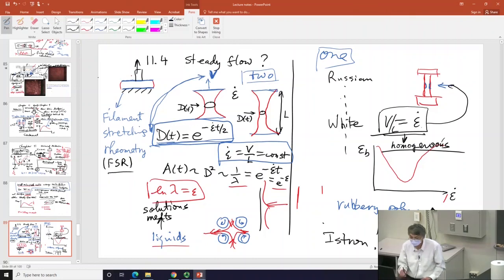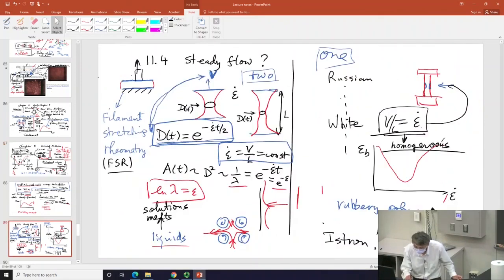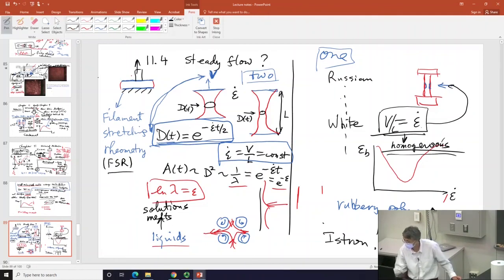And what I just indicated in here by the summary is they never do. Up to some point, after some point, it will break. So on one side, I conclude the sample will break, although you try to maintain homogeneous deformation. It happens for a while, and then it will break.